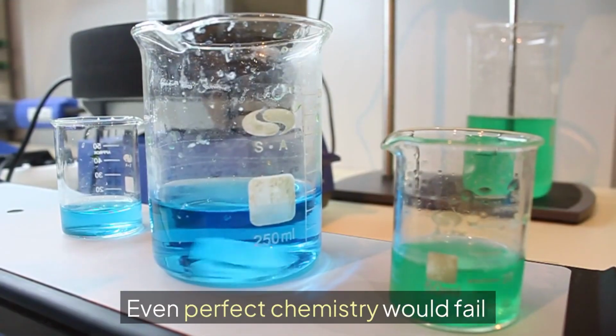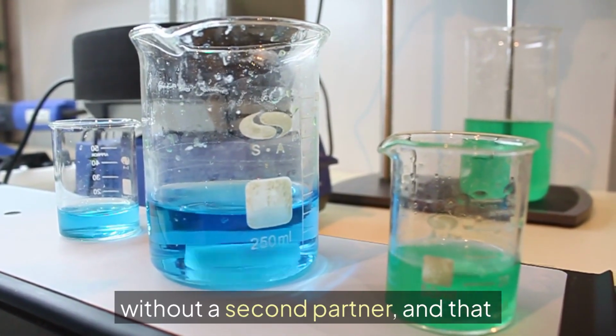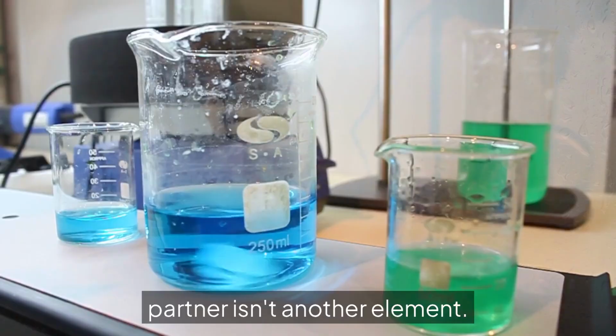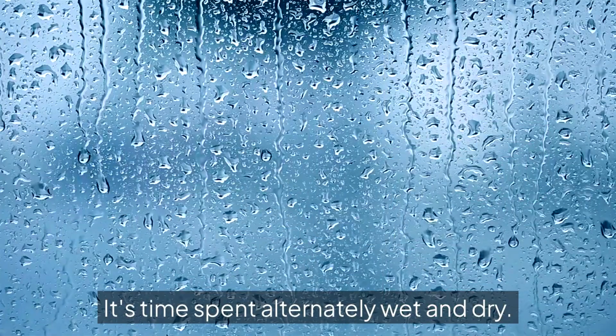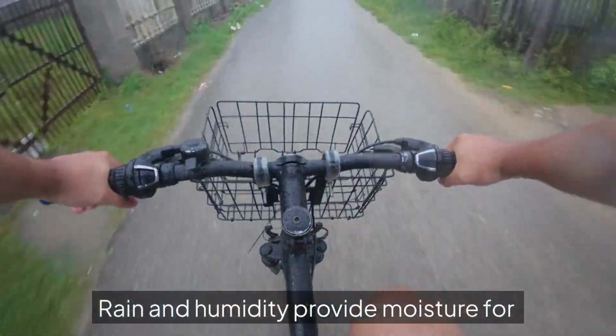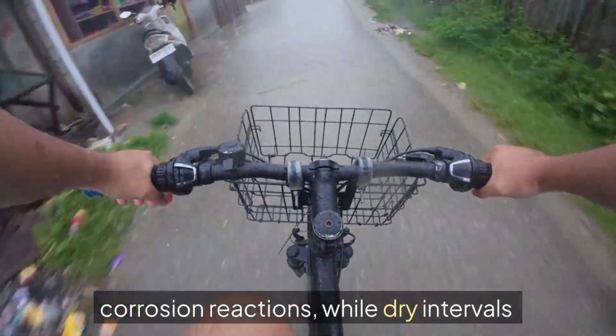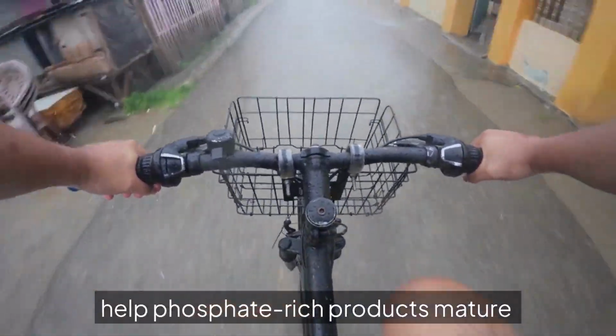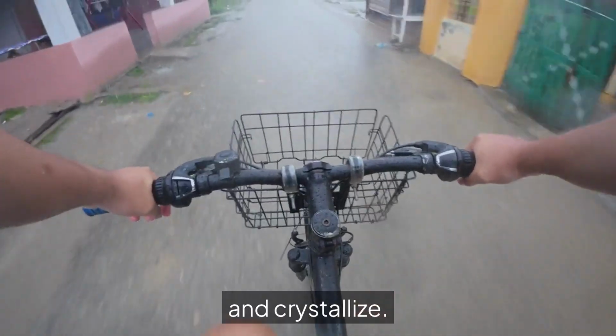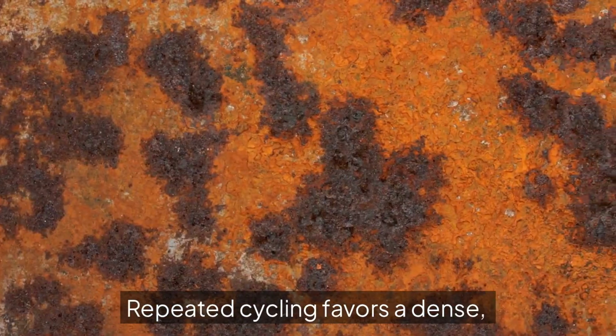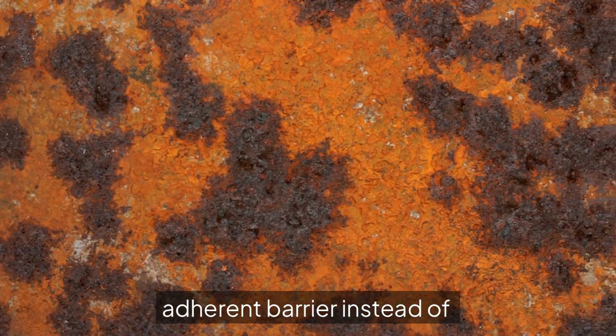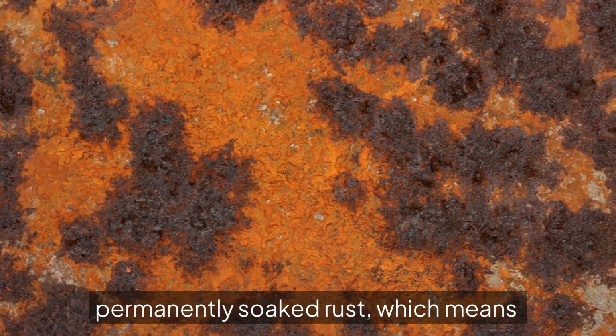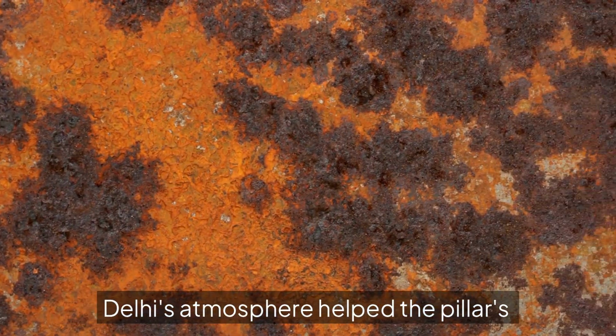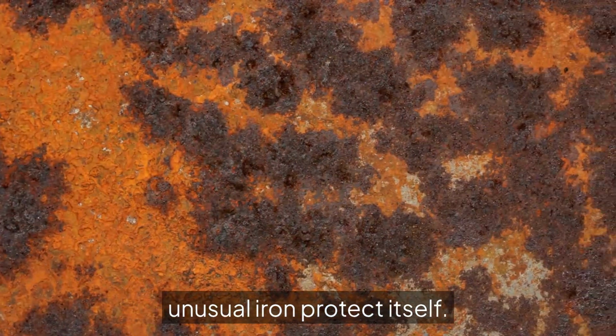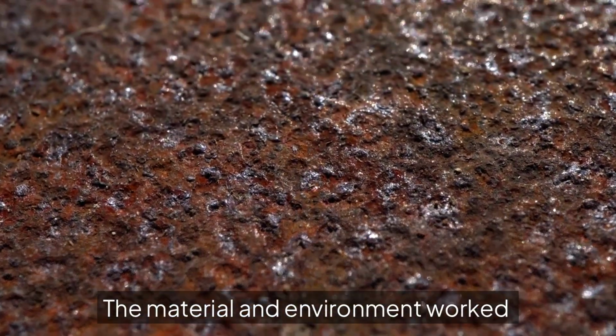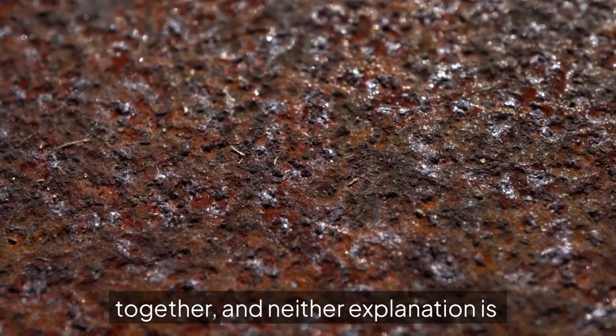Even perfect chemistry would fail without a second partner, and that partner isn't another element. It's time spent alternately wet and dry. Rain and humidity provide moisture for corrosion reactions, while dry intervals help phosphate-rich products mature and crystallize. Repeated cycling favors a dense, adherent barrier instead of permanently soaked rust, which means Delhi's atmosphere helped the pillar's unusual iron protect itself. The material and environment work together, and neither explanation is sufficient alone.